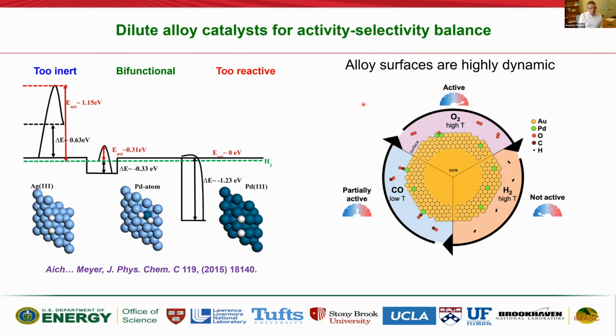So in our work in IMASC a couple of years ago, we found strong dynamic effects corresponding to these dilute palladium alloys. In this case, we experimented with palladium and gold. At different temperatures, in different reaction environments, palladium atoms redistributed on the surface of gold. And we did it using nanoparticles, not surfaces. So, for example, under hydrogen, the catalyst was not active, and this was, I think, the hexyne hydrogenation reaction. And under oxygen, it became active at high temperature and partially active under CO at low temperature. So there was a clear effect of some kind of restructuring of the alloy components on the reactivity. And we wanted to understand also how to capture that and how to understand the role of that for catalysis.